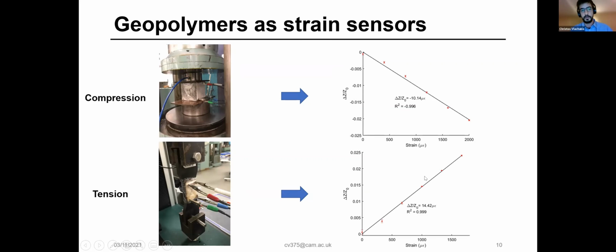And the reason for that is, firstly, under compression, once we actually apply the load and we squeeze the material, let's say, the distances that the ions actually need to move become smaller, and therefore this leads to reduced resistance. In regards to tension, similarly, since we're stretching it, the distances that the ions need to move are increased, and therefore this leads to increased resistance.